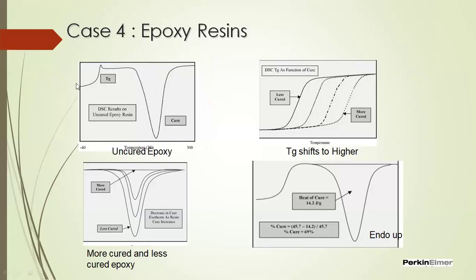Here, endo is up. So what you do, you take your uncured epoxy resin, record a DSC, you get an exotherm. You find out its delta H. Then you cure your material at different time intervals. Again, find out its delta H. Now you know the delta H of uncured material and delta H of cured material. Find out its percentage cure by just taking the ratio of that. Do a DSC. Find out its Tg, because glass transition temperature increases with curing.